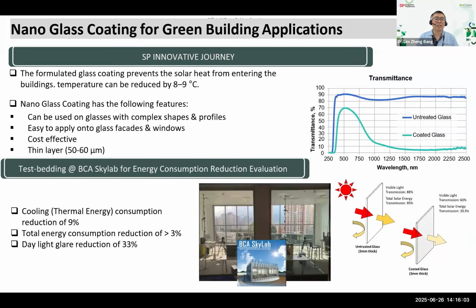Last of the chemicals that we're covering about sustainability is regarding nanoglass for buildings for heat blocking. As you're aware, Singapore is a very hot environment, and this coating can be applied on the interior glass surface, which can prevent the solar heat from entering the buildings. Based on the results, the internal temperature can be reduced by close to 10 degrees Celsius, and it can be applied to different shapes or profiles of glass. And it's very thin, about 50 micron.